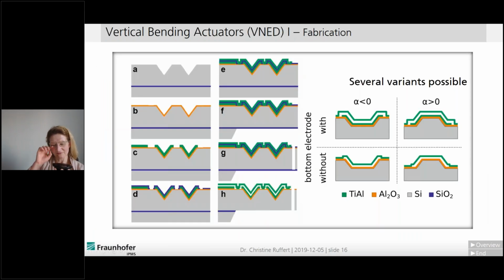So to give you an idea how the fabrication is carried out, starting from A, we take a silicon wafer with buried oxide, which is indicated by the purple line here. Then we do a wet chemical etch by KOH, with an angle of 54.7 degree. And next, the alumina insulation is deposited here on the pattern surface. On the next step, C, the titanium, I already mentioned the first systems were made of titanium aluminide on the top and silicon on the bottom, or even both titanium aluminide. And the electrode material is deposited here.